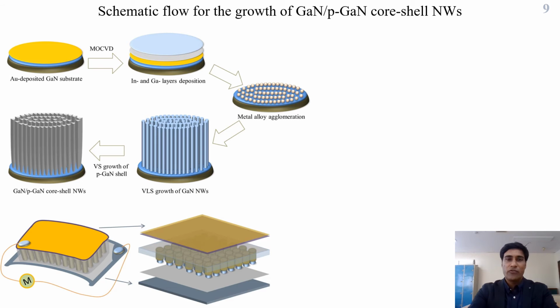This is the schematic flow for the growth of GaN/p-GaN coaxial nanowires. We used Au-deposited gallium nitride thin film. The Au thickness was around 6 angstrom, and then we placed the Au-deposited gallium nitride inside the MOCVD reactor, and we incorporated the trimethyl indium and trimethyl gallium at different temperatures, and then we did the agglomeration at 825 degrees centigrade. Here you can see the agglomeration. So this is the gallium indium Au alloy agglomeration.